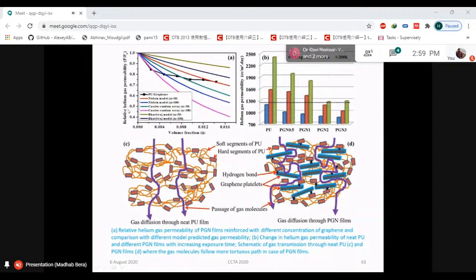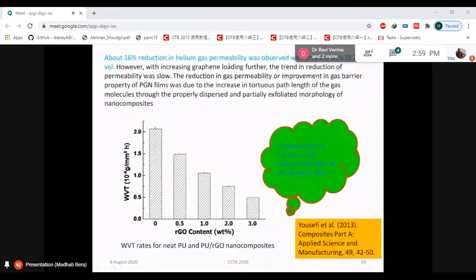the relative helium gas permeability of thermoplastic polyurethane has been investigated, and the exposure to helium gas is varied up to 200 hours. It was found that the gas permeability decreases with increasing exposure time, and this is again similar due to the tortuous path that the gas molecule has to follow. About 16% reduction in helium gas permeability was observed with only 0.5% loading. However, with increasing graphene loading further, the trend of reduction of gas permeability gets lower.